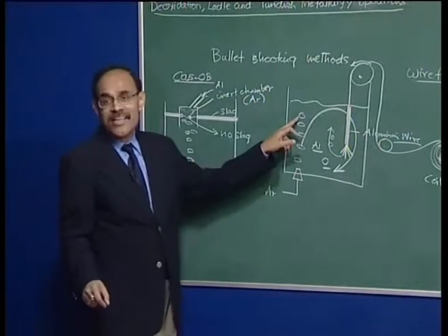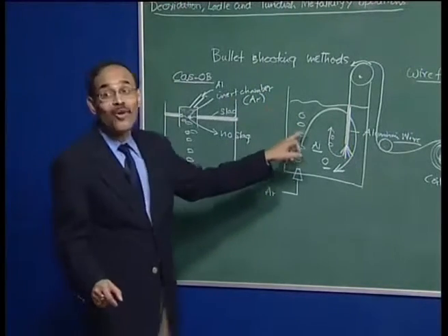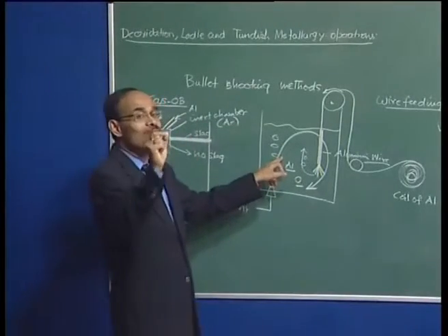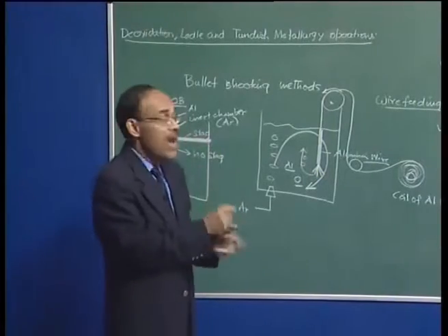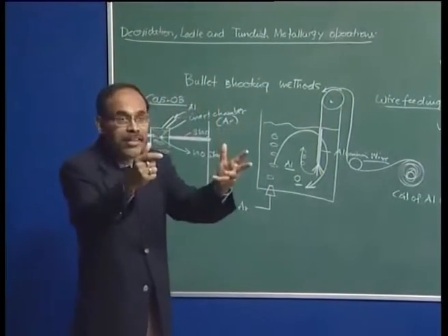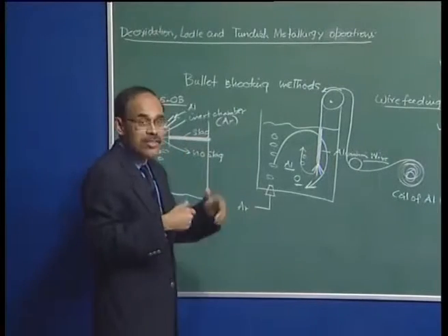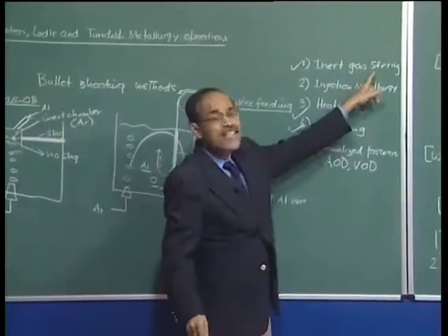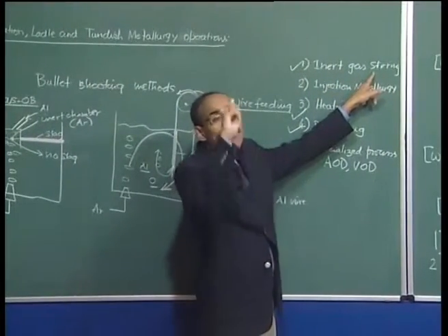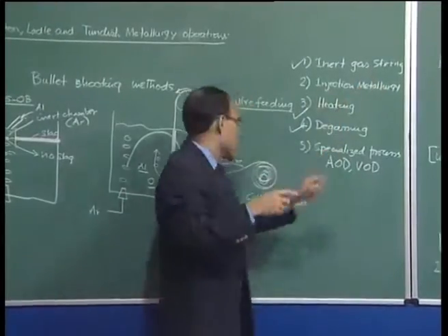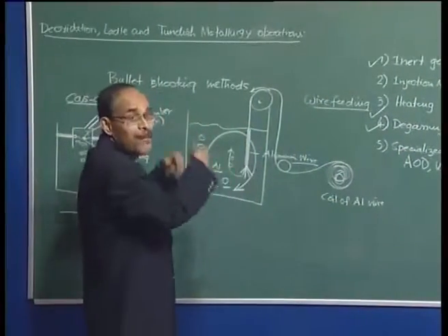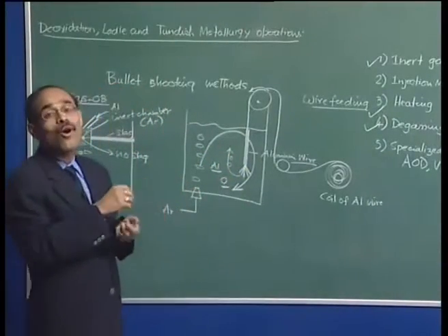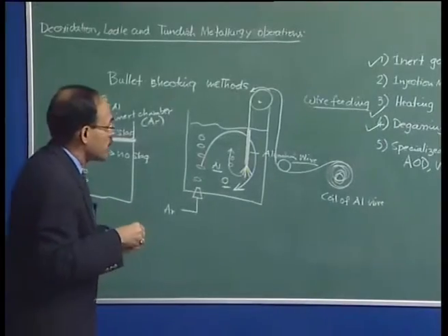And we require inert gas stirring because the inert gas is not going to contaminate molten metal. At every stage from now onwards, we are going to ensure the steel does not get contaminated either from the environment or with the refractory or with introduction of foreign materials and so on. So inert gas stirring is an essential part of ladle metallurgy. The objective is to continuously stir the contents of the bath such that thermal homogenization, material homogenization, chemical reactions, inclusion flotation can all operate with maximum efficiency.